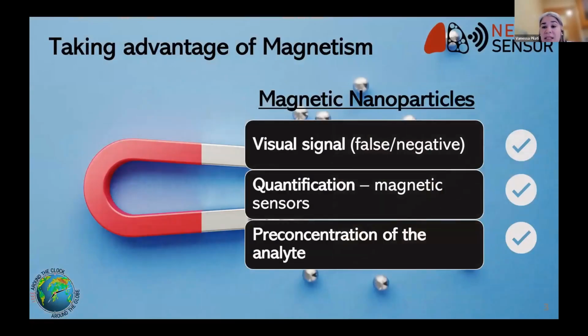However, we can use magnetism in our favor. Magnetic nanoparticles provide not only a visual signal, but also a magnetic one that can be detected and quantified using a magnetic sensor. We can also use these magnetic nanoparticles to pre-concentrate the sample, which is very interesting when we are dealing with complex samples such as blood, where we have a lot of biomarkers. Using magnetism, we can separate them from the other biomarkers and also avoid nonspecificity in the test.